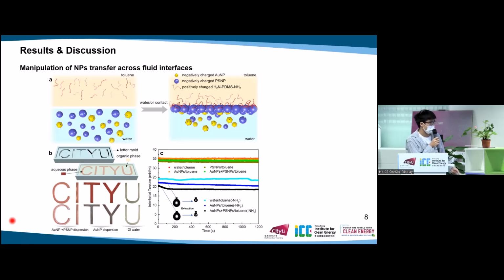compressing the droplet volume of the gold nanoparticle dispersion, we got no wrinkles on the surface of the droplet. However, compressing the droplet volume of the mixed nanoparticle dispersion resulted in wrinkles on the surface, indicating that a jammed solid-like film was formed at the interface, which can block the diffusion of the ligands into the aqueous phase.